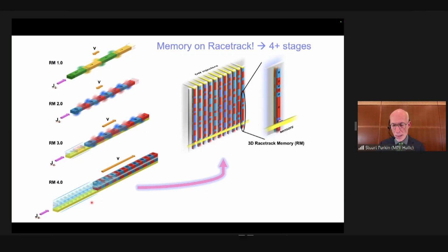That is the objective. And we believe today that we've demonstrated we can move a series of domain walls in these so-called synthetic anti-ferromagnetic racetracks at speeds exceeding 1 kilometer per second, 10 times higher than was possible 20 years ago when we started. So in 2008, we demonstrated for the first time that using the principle I discussed, the spin transfer of angular momentum from spin polarized current passing through a magnetic film, we could move a series of domain walls together. But the speed was limited by the amount of spin angular momentum from the current.